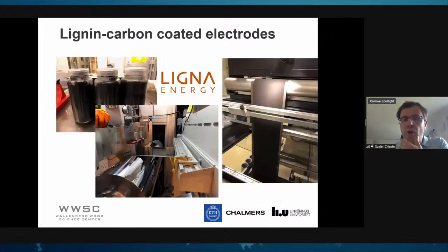So this kind of very cheap material has been used by the startup Ligna Energy in Norrköping, and they've formed many kilograms of that and basically print or coat, in a roll fashion, these kinds of lignin electrodes. So recently they've obtained 30 meters of this as a test run. And they are working quite well, so they're very reliable. So this is an interesting track that still needs to be improved.